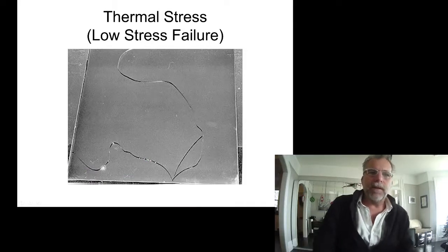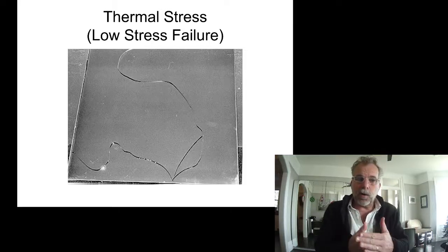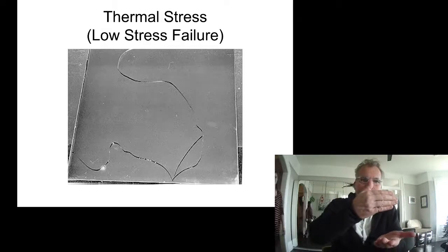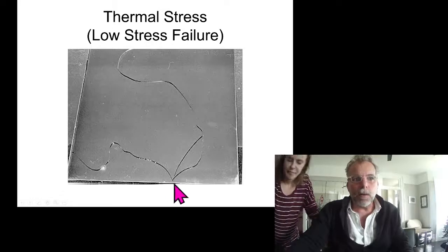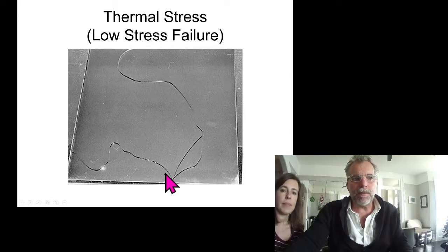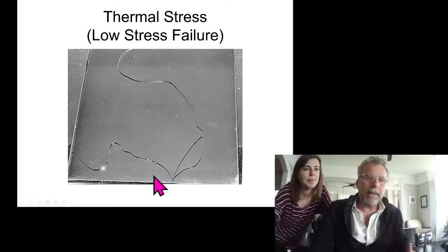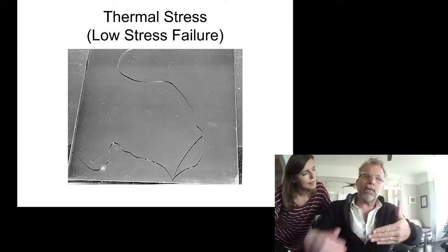Thermal failures can be caused by a number of things. It can be caused by a cold bridge. Say you have an aluminum window frame, and the glass is accidentally in contact with the window frame, you can get a cold bridge, which will precipitate a thermal failure. It'll wander away from the edge. It can happen if you have a glazed wall with an overhang.